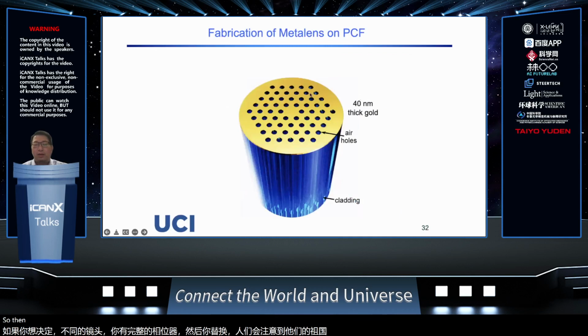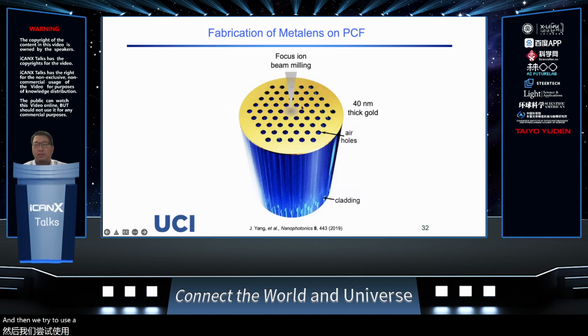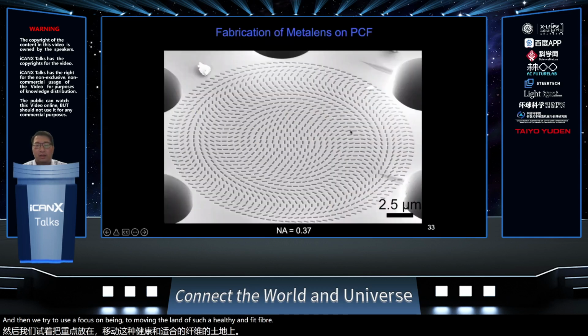So then the way we make the lenses is using a photonic crystal fiber. I'll skip the reason here, but basically we can have a bigger core size. What we do then is coat the metal on the surface, and then use a focused ion beam to mill the nanostructure on the end face of the fiber. So then my student was able to make a really beautiful structure.